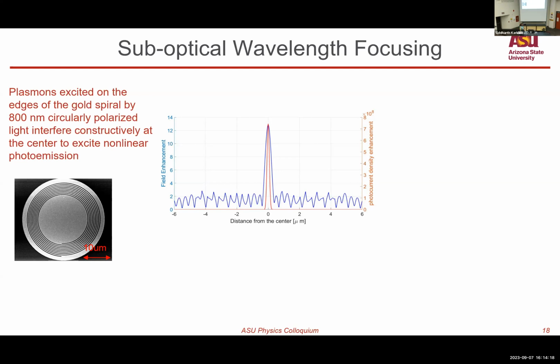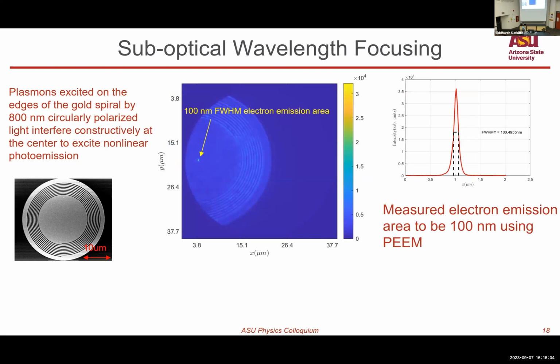Now, this is 800 nanometer light, so you can't expect to get linear photoemission. However, if you have very intense light, you can get higher order photoemission. And in this case, we get fourth or fifth order photoemission, and the current is proportional to the intensity to the power of the nonlinear order of photoemission. So when it comes to the photoemission spot size, it becomes intensity to the power four if it's a fourth order photoemission, and we get a very small electron spot of 100 nanometers full width half max. We were able to measure such a small spot in a photoemission electron microscope in our lab. And this is the tiny, tiny electron spot that we were able to get.